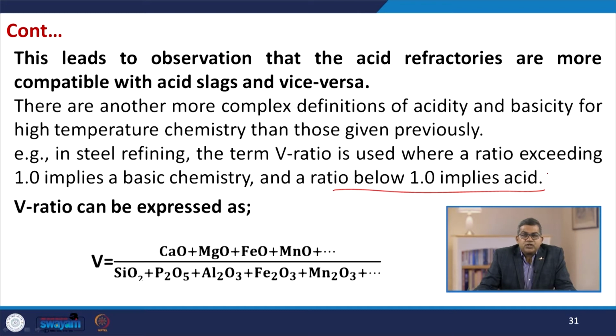Now, the question arises of how we can express the V ratio. The V ratio is expressed as V equals CaO plus MgO plus FeO plus MnO plus and so on, over SiO2 plus P2O5 plus Al2O3 plus Fe2O3 plus Mn2O3 plus and so on.